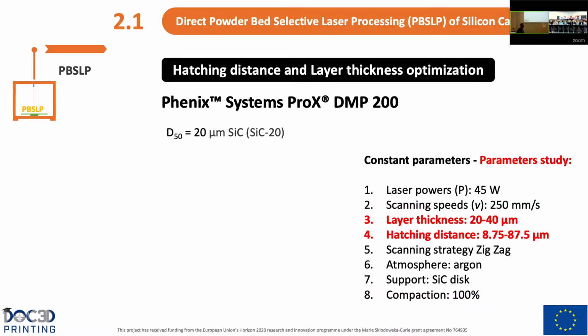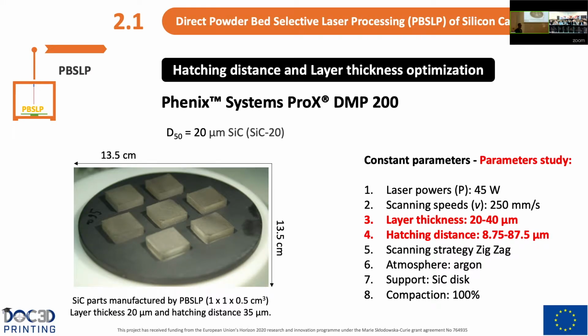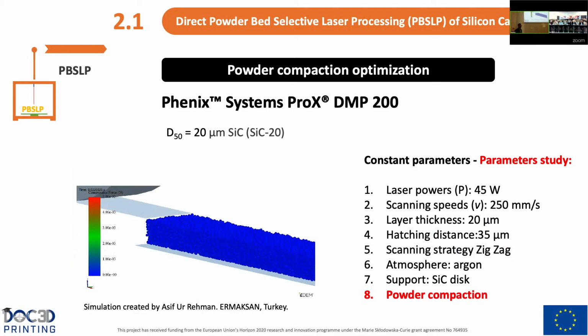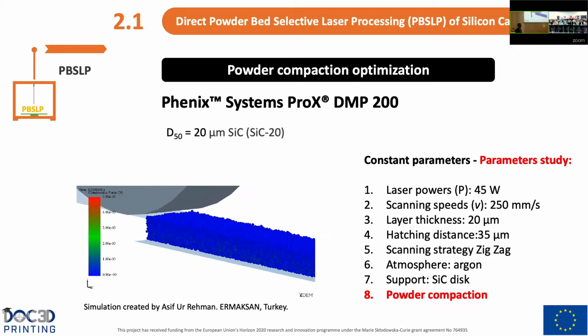So next, regarding the optimization of layer thickness and hatch distance, we achieve good reproducibility and good relative density by using parameters of 20 micrometers and 35 micrometers of layer thickness and hatch distance, respectively. And finally, we have to optimize, of course, the powder compaction.